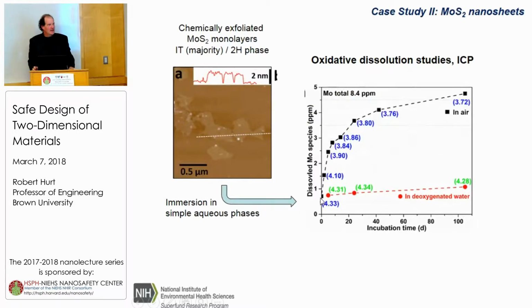If you take the metallic sheets and dilute them into an aqueous buffer, here's the dissolved molybdenum as a function of time. You see a slow increase in that molybdenum, and it starts to approach the total molybdenum concentration of 8.4 ppm. Now, this is a very slow process. This is 100 days. So if you're very patient, this material will go into solution, the pH dropping.